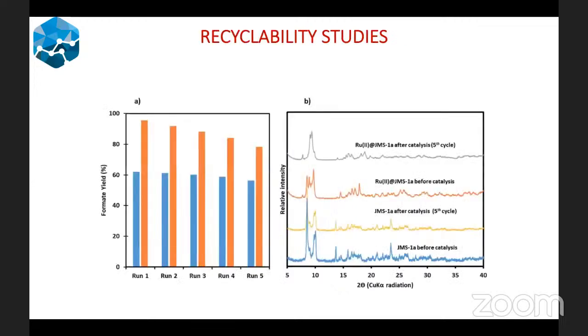And then we checked the recyclability studies. We looked at both the pristine MOF as well as the ruthenium functionalized MOF. As you can see, the as-made MOF is very much stable over the 5 runs, whereas the ruthenium functionalized MOF showed some decrease, or a gradual decrease, in the catalytic activity.